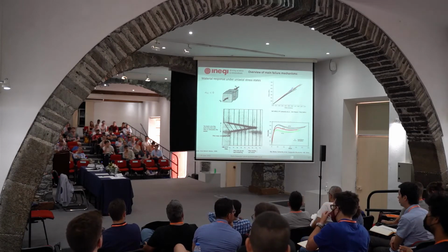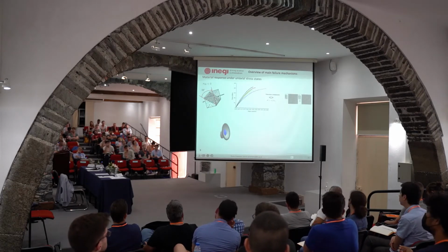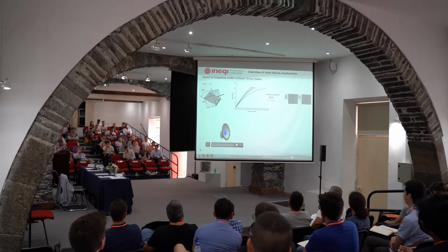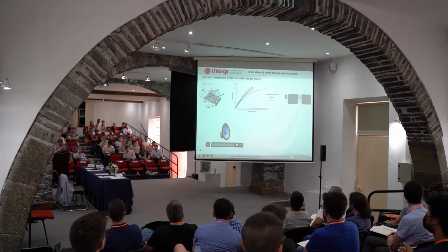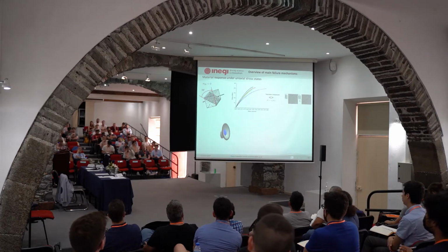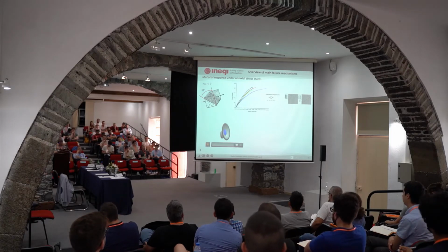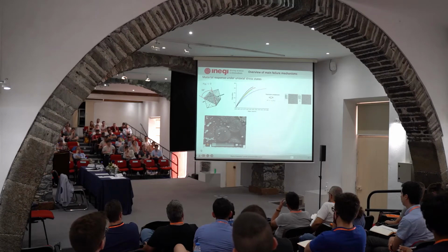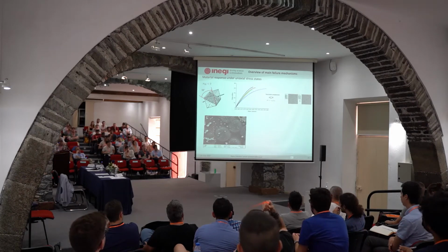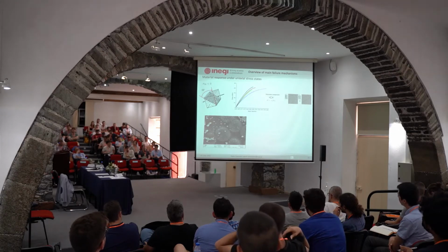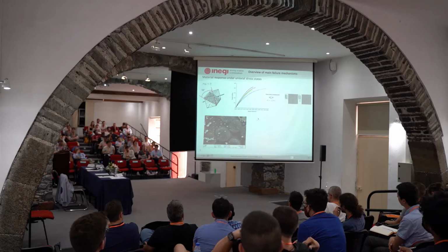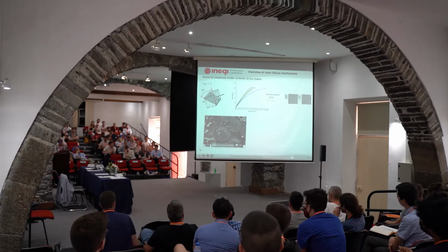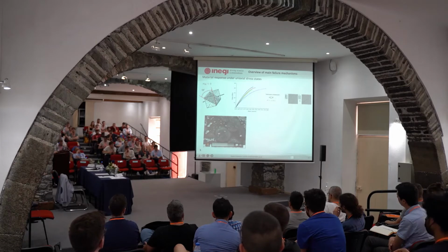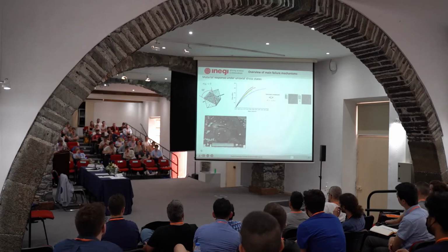So we wanted just to make sure that the models that we used for the resin were accurate. Okay. But here what we did, this is an interesting experimental data. With some colleagues from Louvain-la-Neuve in Belgium, the student Jeremy Chevalier and Professor Thomas Pardoen, what we did was... I'll start here. You can see this is not a simulation, this is an experimental test that was conducted inside an SEM, but with a speckle pattern, right? So we could use DIC, digital image correlation. We're loading the specimen inside the SEM, and we are getting the displacement and strain fields. And we could see the crack at the interface. I'll play it again. If you look at this interface, this is where the crack will start, and then it will propagate into the matrix.